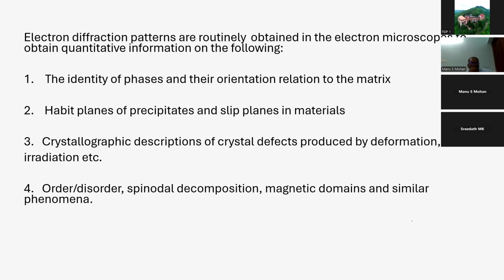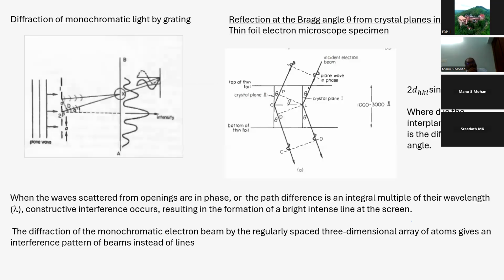If you have a material like steel which will be put in nuclear reactors, you definitely have radiation induced defects - any vacancies, any Frenkel defects, any radiation induced defects. That time you have to go for TEM. Order-disorder transformation, spinodal decomposition, magnetic domains - all those things also require TEM.